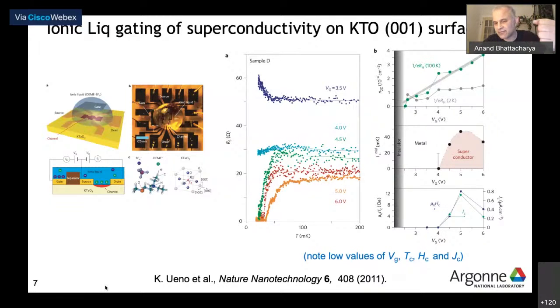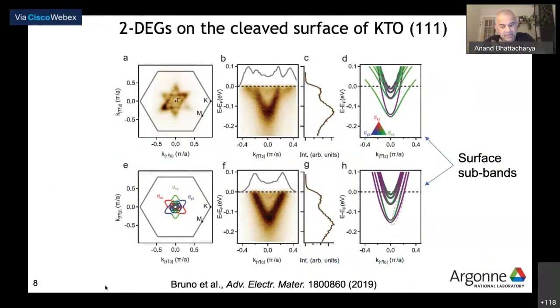And this sort of remained a flag on KTO that, yeah, it can go superconducting, but not much happened since. Okay, so a little bit more about the electronic structure of KTO. The 111 surface of KTO is a little less studied than the 001 surface. So it turns out you can make electron gases on KTO by cleaving and by exposing to UV light and such. And people have done this and they found electronic states at the surface. They found a Fermi surface with photoemission. Without going into these details, you can see the 6-fold symmetry, it's confirmed, it sort of lines up with what people expect from DFT and such, and they see these states, and not only that, they can sort of see the mini bands that form near the surface when you have confinement.